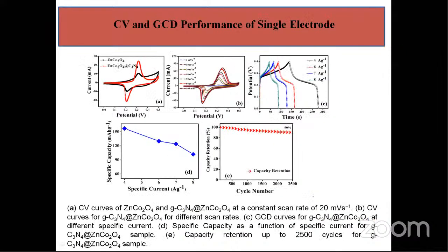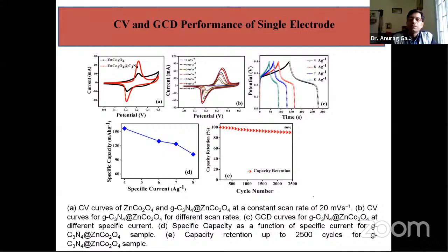Then we see the CV curve and GCD curves for these energy storage devices. You could see this is the CV curve. In the CV curve, clear peaks are visible for oxidation and reduction. So immediately you could say it's not an EDLC material. There is no electrostatic charge storage here. This is electrochemical charge storage, because oxidation and reduction take place, but it is not purely battery type. How can you identify this? Because the peaks are not as sharp as in batteries. So you could say it's a combined effect. It is a pseudocapacitor.